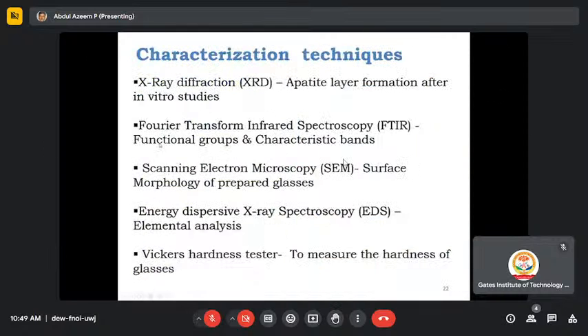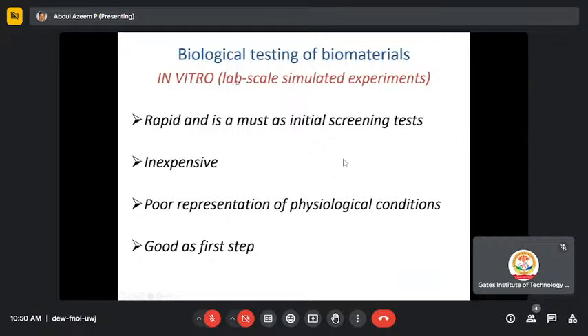So we are using different types of characterization techniques like XRD for formation of the apatite layer. We are using FTIR for the functional and characteristic bands. As I mentioned, we are using FESEM in our department to study the surface morphology of the material, and then EDAX for the elemental analysis. And the mechanical department has a universal testing machine and a Vickers hardness tester, by means of which you test the hardness and the other mechanical properties of the material.